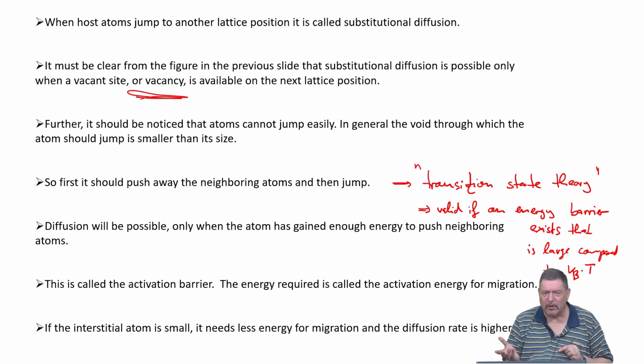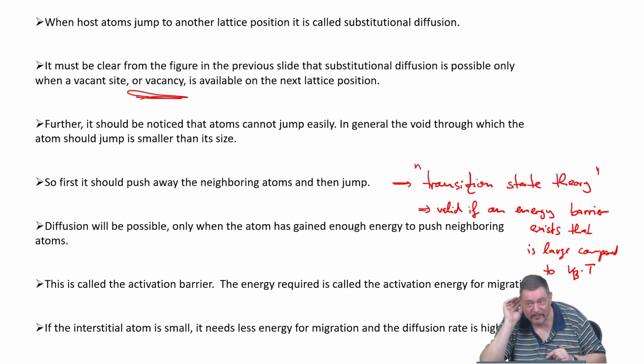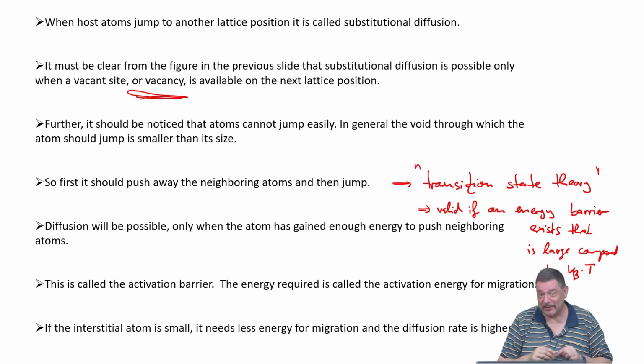There's a very famous law. Arrhenius? Yes, very good. So it's the Arrhenius representation, which goes back to rare event statistics and transition state theory for processes which are dictated or limited by activation barriers that are large in comparison to kBoltzmann times temperature. So all the processes I know that follow this statistics can be described by Arrhenius law in terms of activation, right?